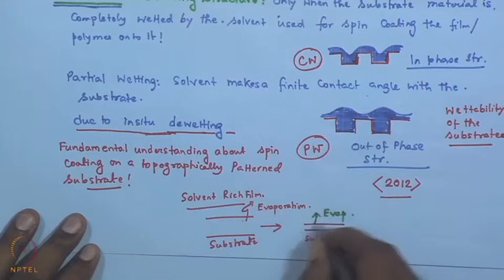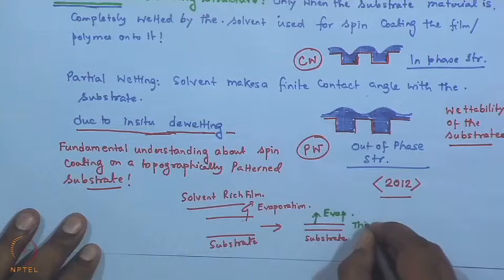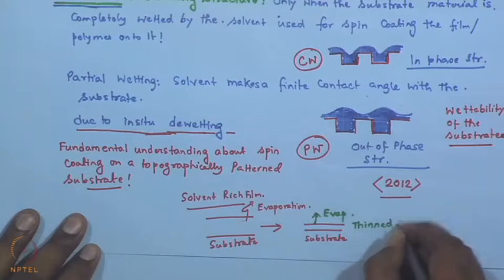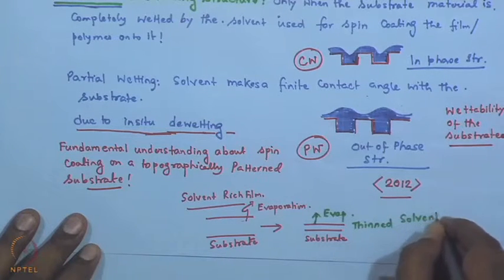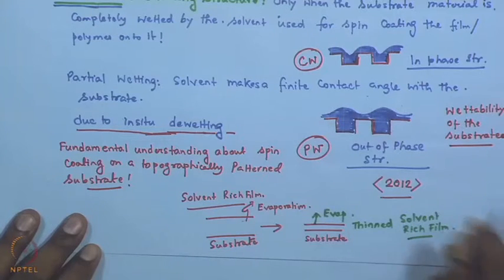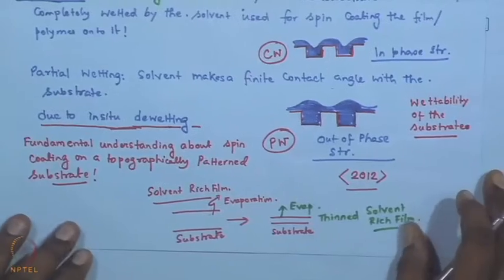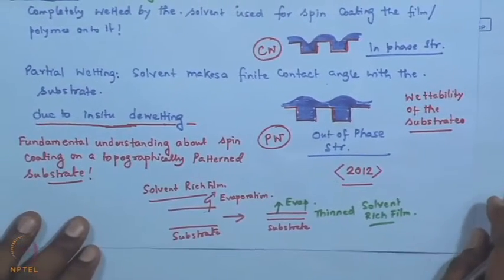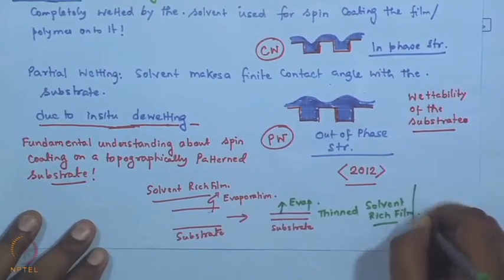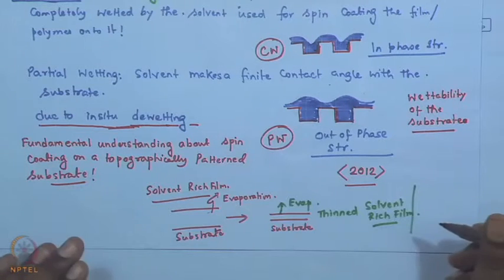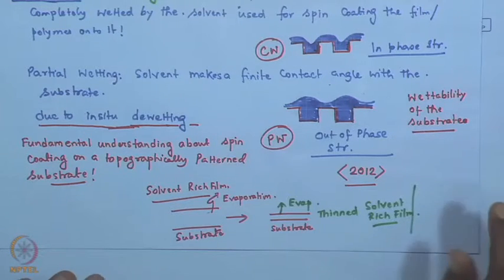And once this layer has now become thin, but still it is rich in solvent, its entire hydrodynamics is governed by the hydrodynamics of the solvent, that is the wettability of the substrate by the solvent, and all these things are still dominant.